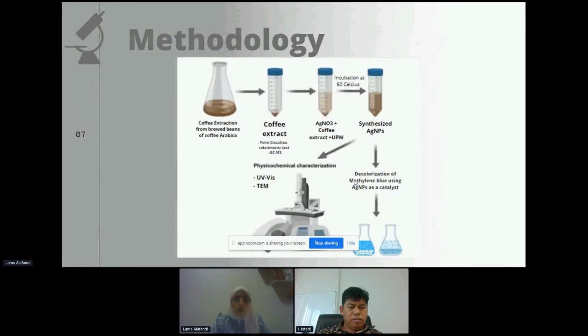Moving to the general overview of the methodology, first, we obtained the coffee extract. As mentioned before, it was diluted with ultra pure water, precipitated for 48 hours, and then filtered, and that's how we got our coffee extract. After the coffee extract was ready, we used the Folin test to test the phenol content in the coffee extract and GCMS to analyze the content of the coffee extract. Then the coffee extract was added to the silver nitrate to synthesize silver nanoparticles, and we will go into more detail about the parameters of the reaction in the next slide.